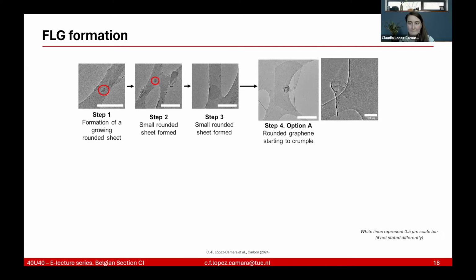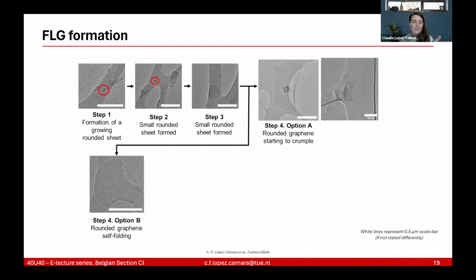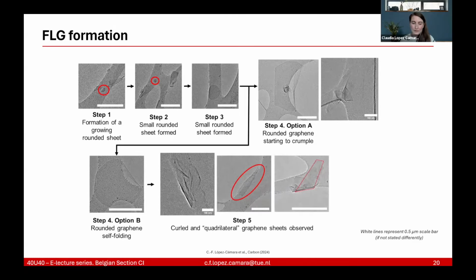Not nicely, let's say. But in some cases, instead of crumpling in a random way, we were seeing that this rounded graphene was folding actually nicely. It was self-folding nicely, as if it was, for example, an envelope, if you want to think of it this way, as you can see in this picture. And in these cases that the graphene was folding nicely, two things could happen. One was that you would get curled graphene, graphene that was curling into itself, as you can see in the video that I will play in a moment.